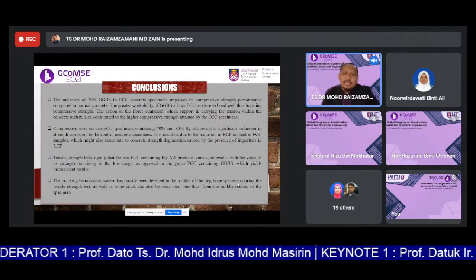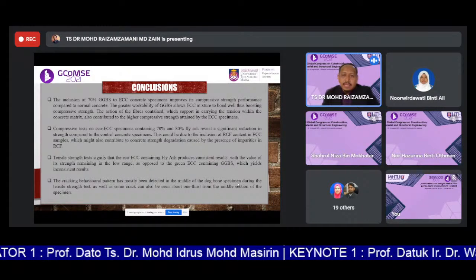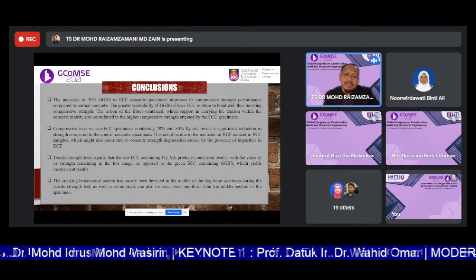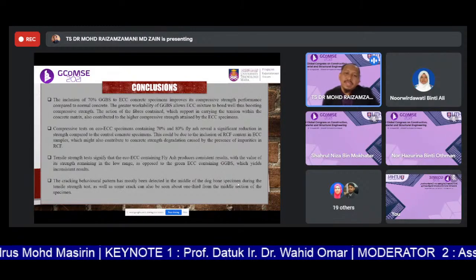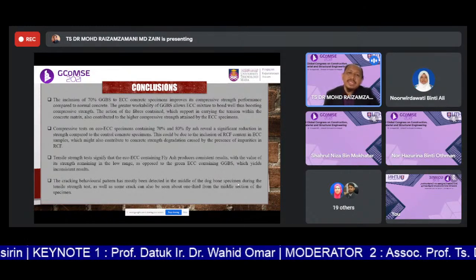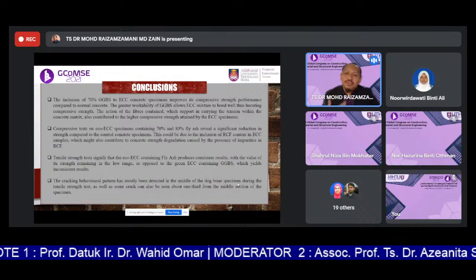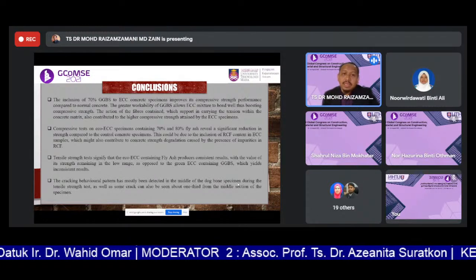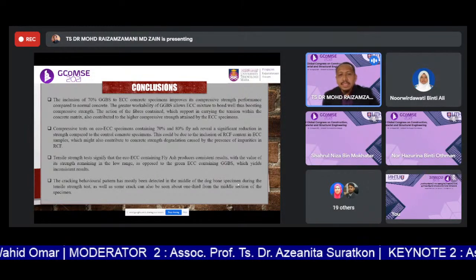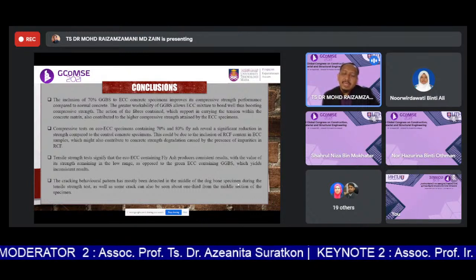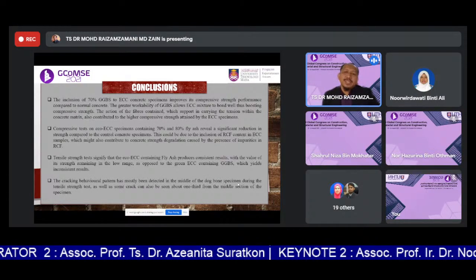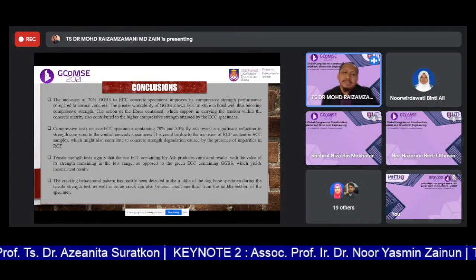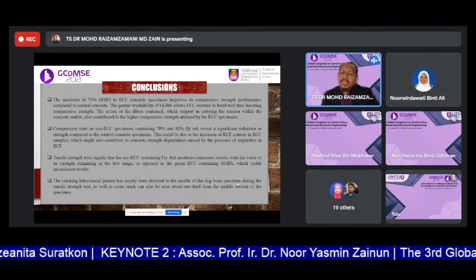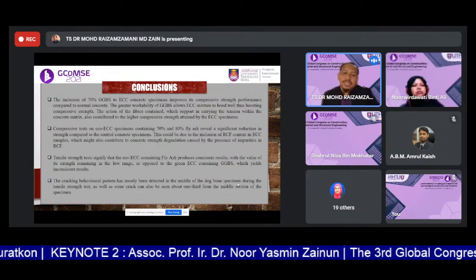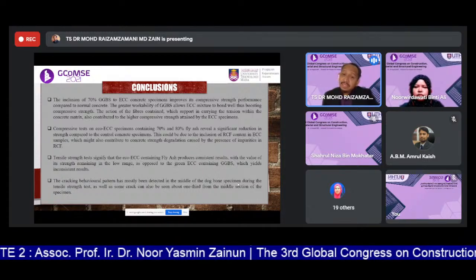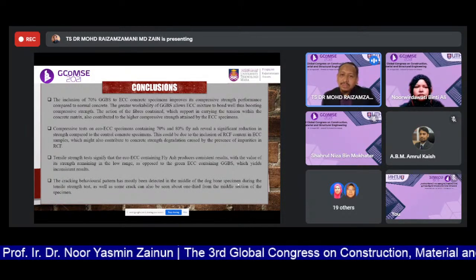Okay, now let's look at the last part, the conclusions. Based on the experimental studies here, the inclusion of 70% GGBS in ECC concrete specimen improves its compressive strength performance compared to the normal concrete. The greater workability of GGBS allows the ECC mixture to bond well and thus boosts the compressive strength. And compressive tests on eco ECC specimens containing 70% and 80% fly ash reveal a significant reduction compared to normal.